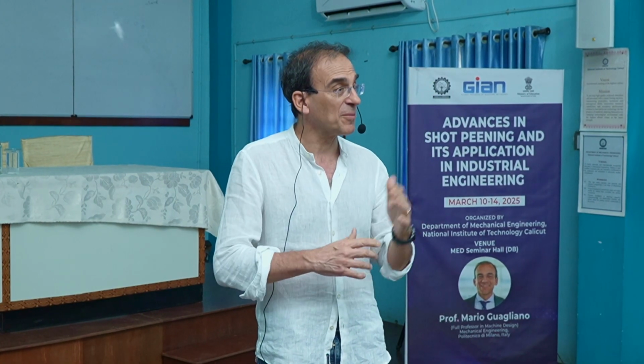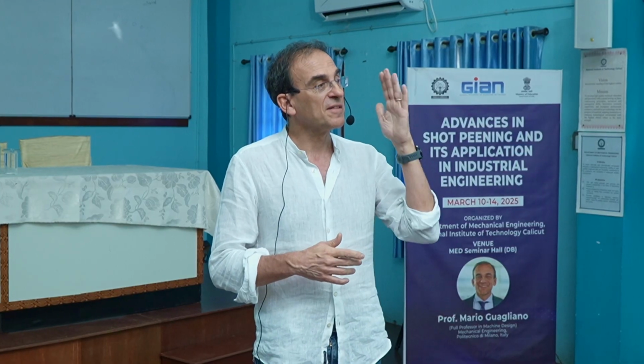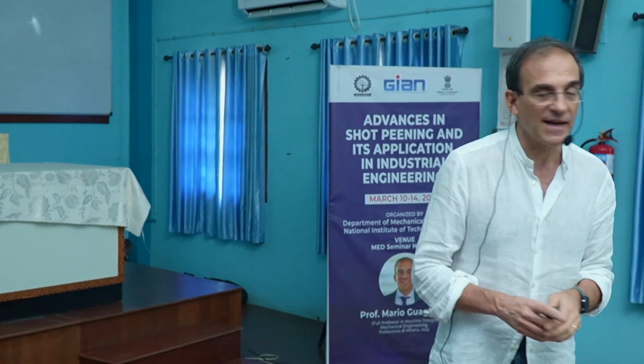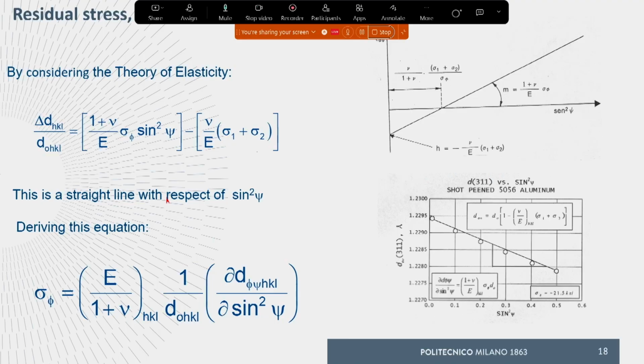So it is allowed to consider the first D that we obtain as D0, and then use the other ones to calculate delta D. So, by means of the law, we are calculating delta D according to different psi, and by deriving the straight line, we know that the slope is related to sigma phi.